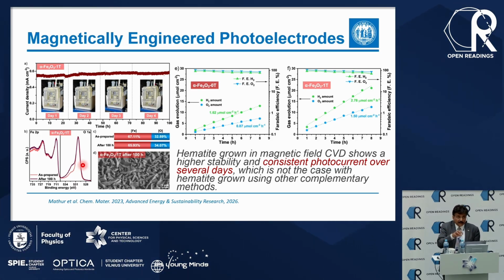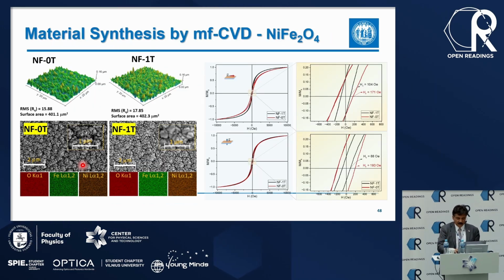Now, iron oxide is good, as I said, but you have to make it better. And this is what people are doing by doping. You take the lattice and you add something with a different valency so that you have an electronic disorder. For example, you can put nickel in it. And by looking at the magnetic studies, you see that the magnetic memory of that material is now changing, because you now have a different domain structure, so the coercivity values are changing.